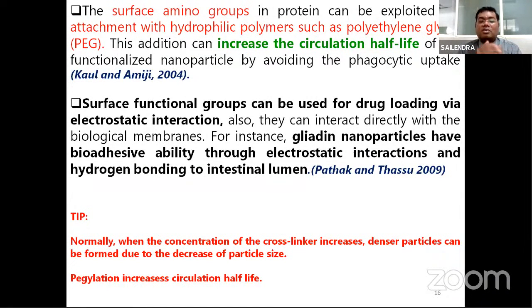Increase the charge. Suppose you are doing this DLS particle size analysis, where you measure the zeta potential of the nanoparticle. If your zeta potential of a nanoparticle is, suppose, minus 29 or minus 30, at that level, no two nanoparticles will come close to each other. But the surface charge is so negative that if you give a drug molecule which is positively charged, immediately it will go and be attracted to the negatively charged surface, and immediately it will have an electrostatic interaction and it will be adsorbed on the surface of the nanoparticle.